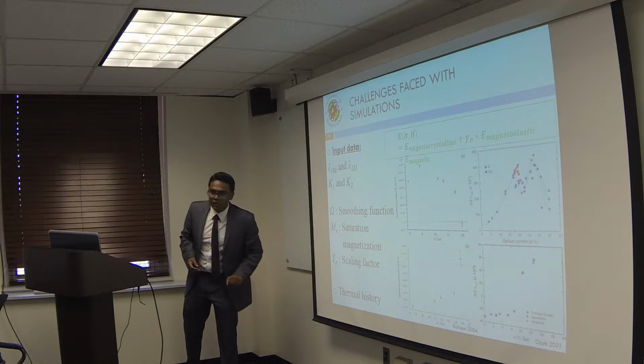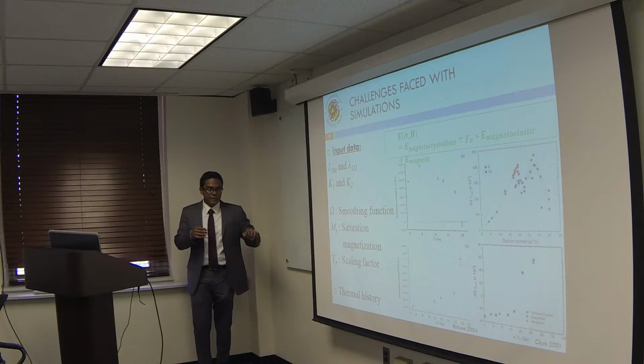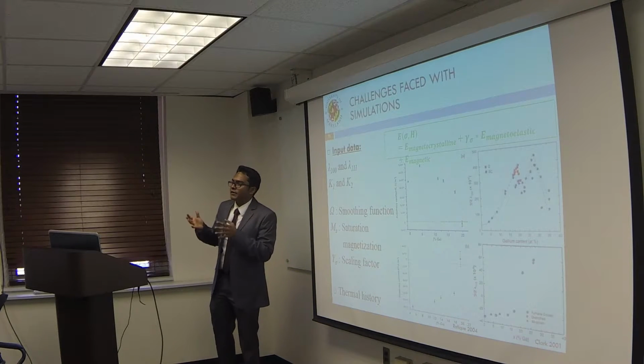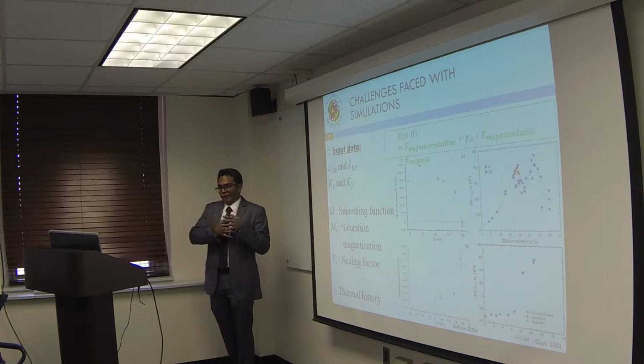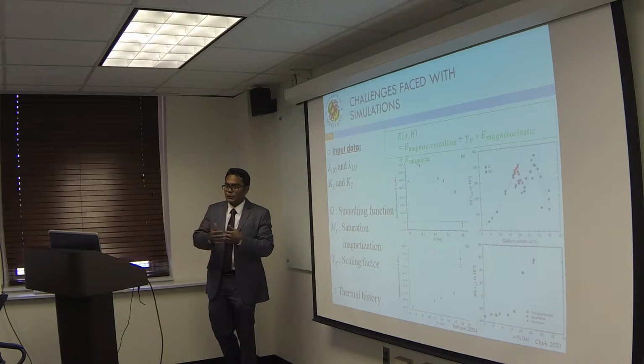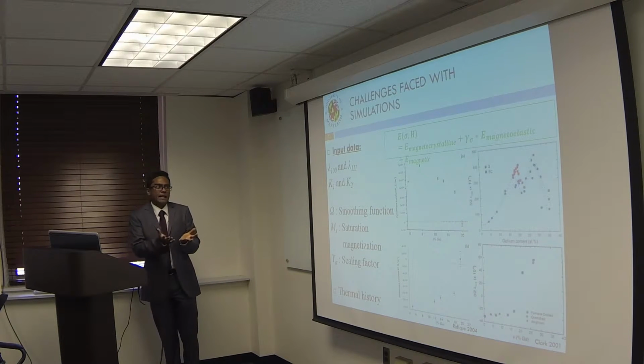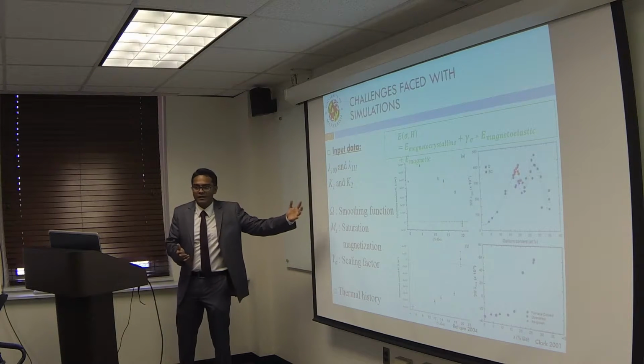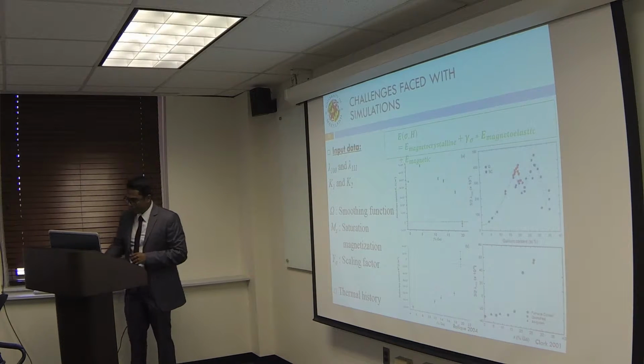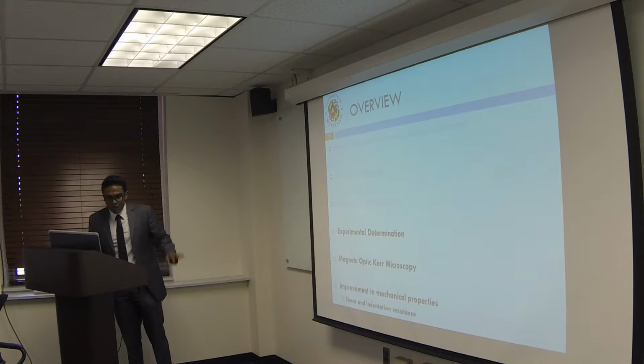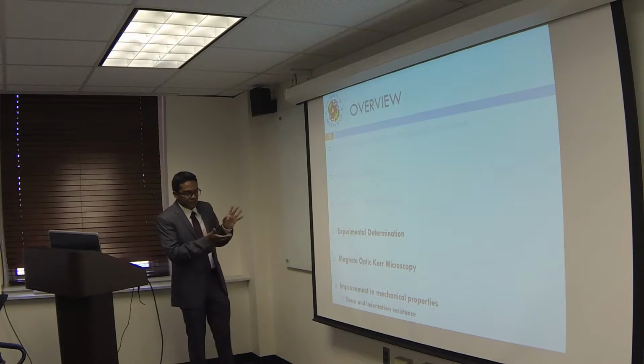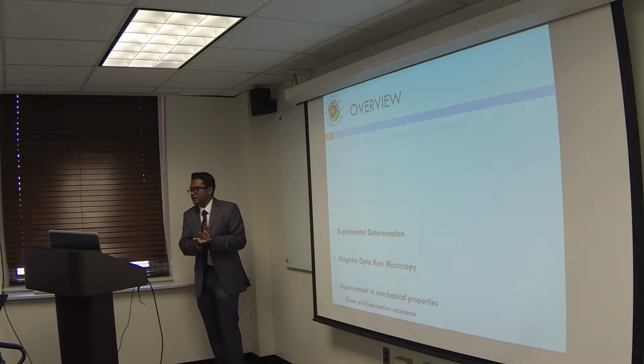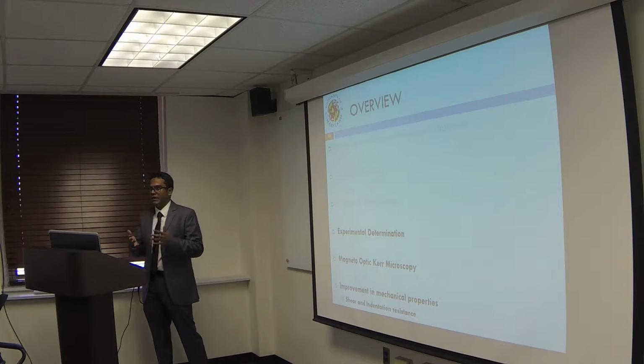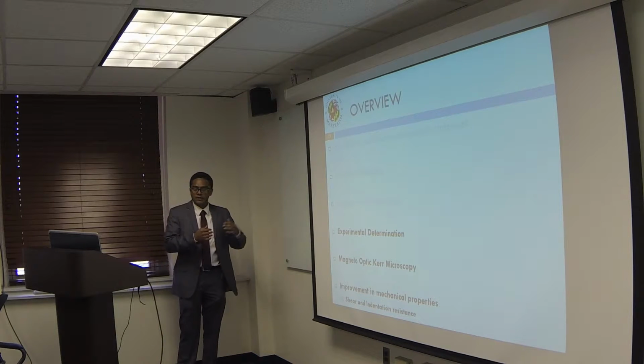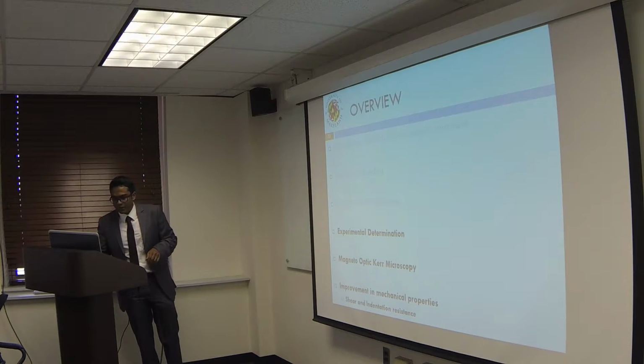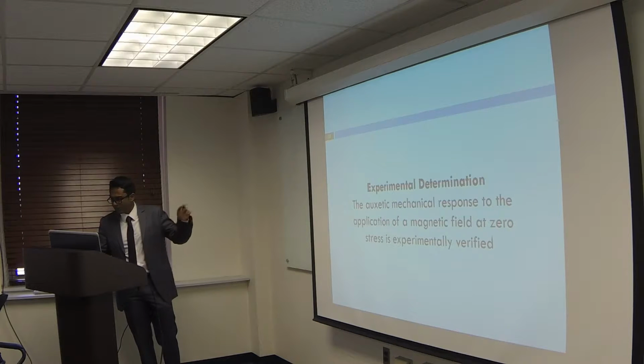But the biggest problem that I faced with the simulation was that the simulation does not directly account for the thermal history of the sample. So if a different protocol was used to heat treat the sample, it does not directly reflect in the inputs that go into the simulation. I'm not going to show you the results from the simulation just yet. I'm going to discuss the experimental part of it and compare the results from my experiments with the simulations. So let's jump into the experimental part of the research.